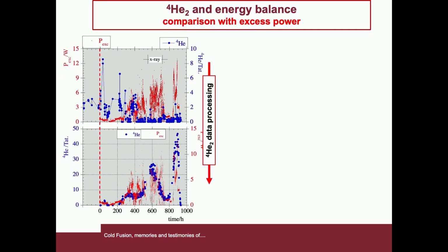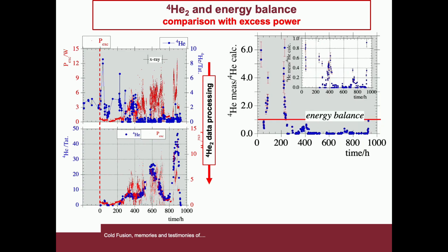Helium-4 and the energy balance, comparison with excess power. Through the previous correlation, it can be seen the transition from the upper graph, which represented the experimental trend of the excess power and the measurement of helium, to the lower graph, where the time correlation between the helium and excess power is reported. As a result of the elaboration that we have done to the model, it can be seen that there is a rather significant correspondence between the excess power and the helium.